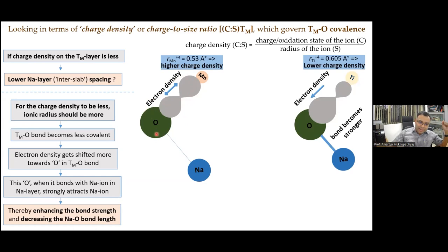As I told, if we increase the covalency of this bond, my oxygen ions have less effective negative charge and the sodium-oxygen bond is weaker and longer. Whereas if I decrease the covalency, then my sodium-oxygen bond can be stronger and shorter. Now that can be done if we take the 3d transition metal ion period, then along the period and a little bit towards both sides of the period, if we select ions such that we go with a lower charge density. When I say lower charge density, I mean lower charge to size ratio. Suppose this is +4, this is +4. Whereas titanium +4 has a larger ionic radius, manganese +4 has a smaller ionic radius.